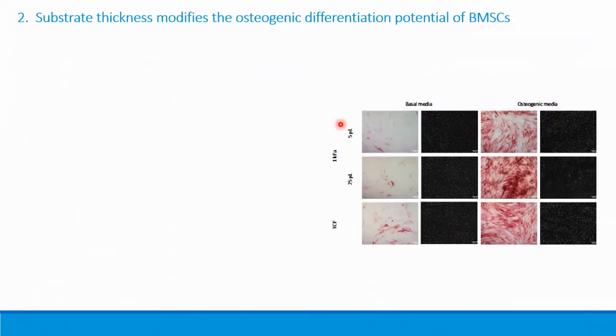After confirming the osteogenic differentiation potential of these cells on tissue culture plastic, we found that bone marrow stromal cells can also differentiate into osteoblasts when changing hydrogel thickness on soft gels. We can clearly see that they proliferated more on thinner gels, and they also increased their osteogenic capacity on soft, thinner gels.